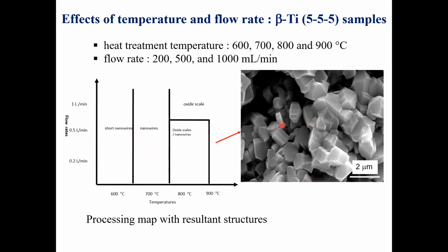And from this, we figured out that as you're increasing the temperature, you're actually increasing the probability of oxidation from other surfaces. So while at 700 you preferentially oxidize on the top, so you keep on growing one-dimensional structure, as you go up in temperature, you are also oxidizing from other surfaces. So it prefers this equiaxed growth rather than an anisotropic one.